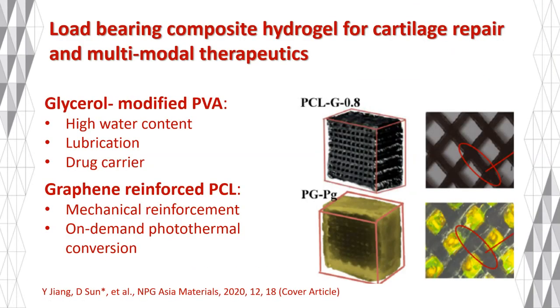2019. In another study, we focus on the development of multifunctional composites for the repair of load-bearing cartilage. Unlike hard bone tissue, damaged cartilage, especially load-bearing cartilage, cannot undergo a natural healing process. Natural cartilage is characterized by its high water content, which can contribute up to 80% of its wet weight. To address this, we designed a cartilage replacement implant utilizing glycerol-modified PVA to enhance the water retention.